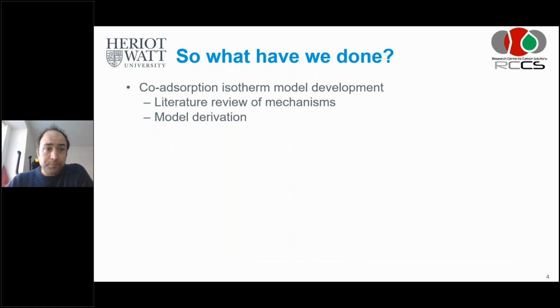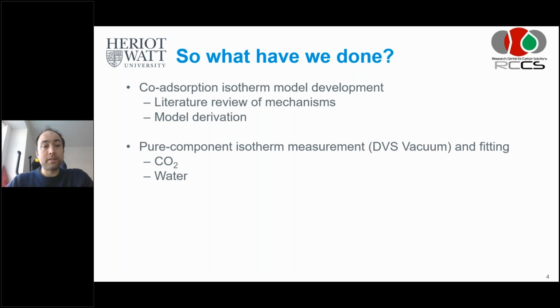So what have we done? We started off with co-adsorption isotherm model development. If we're talking adsorption, then one of the most fundamental things are the isotherms, which basically dictate how much CO2 or water or whatever adsorbs onto a solid surface at a given temperature and at a range of pressures. So what we did is a literature review of potential mechanisms for the co-adsorption of water and CO2. And then we derived a model to describe that. And then we went on to do pure component isotherm measurements with the DVS vacuum, and we fitted isotherm models for that, for water and for CO2.